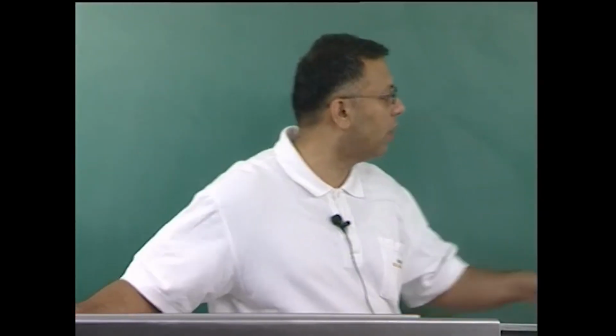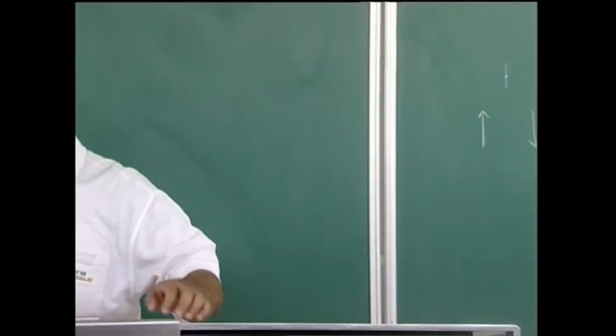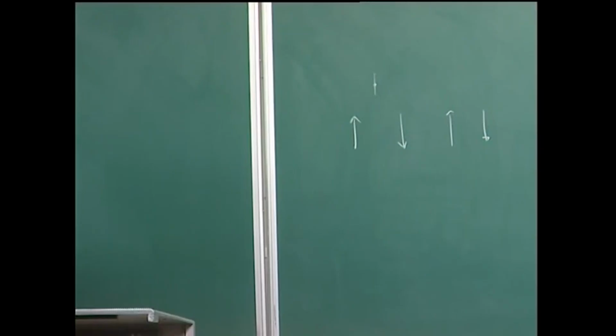That means this is not a simple antiferromagnet which can be drawn like the picture we saw before. The underlying spins have a spin density wave, and this spin density wave, as I pointed out, can be incommensurate with respect to the underlying lattice, and this gives rise to the antiferromagnetism in chromium.